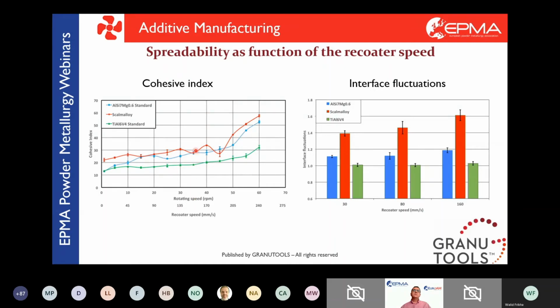Now what you can notice is that the difference between the blue and green line is way higher in the interface fluctuation than in the cohesive index. And the question is why, of course. The reason is the cohesive index inside the rotating drum only takes into account the powder and the speed, that's it. But the interface fluctuation is a picture taken inside the machine, so it's taking everything into account - the powder, the speed, the shape of the recoater, the material of the recoater, the layer thickness, all the process conditions. So the interface fluctuation method is way more precise, of course, but you need to fill the printer with powder, and the goal is not to fill the printer with powder.